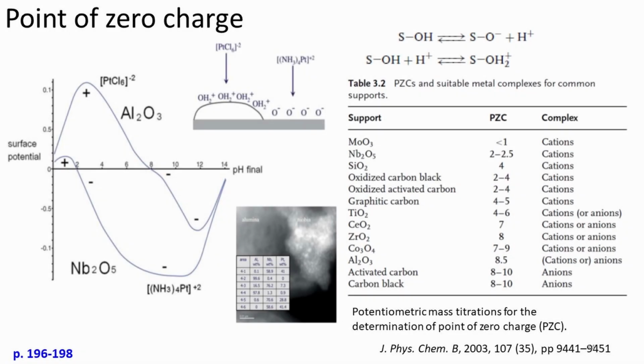This method can also be applied to supported oxides, as illustrated in the figure. Since niobium has a very acidic point of zero charge and alumina a basic one, there exists a wide pH range over which the respective oxides carry opposite charge. Between pH values of 2 and 8, the niobium surface will be negatively charged and the alumina positively charged. If niobium is considered the promoter phase and it is desired to have the promoter in close proximity to the platinum site, a cationic precursor could be chosen and it should be adsorbed selectively on the niobium phase.